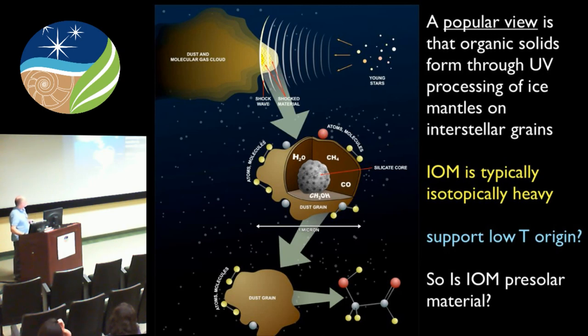So one of the things that is favorable about this is that IOM, as Connel and many other people have shown, going back to the 80s and beyond, tends to be isotopically very heavy in terms of hydrogen isotopes. Deuterium is the least abundant stable isotope in the periodic table. Getting anomalously heavy deuterium values in this material suggests very low temperature sources. And that's absolutely true. And so it supports, at some level, a low-temperature origin. So the question is: is IOM pre-solar material?